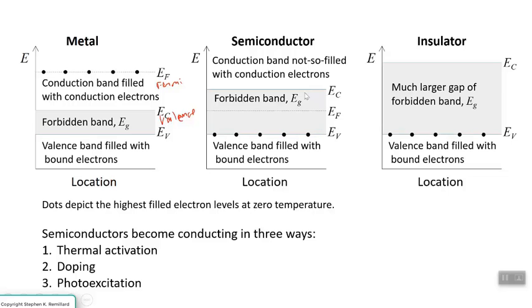which is what we practically do with semiconductors, where we put states in the gap and then have a very small ionization energy to get electrons in the conduction band. And then there's photoionization, where you send a photon along and it hits a valence electron, and it gets knocked into the conduction band. That's the principle of operation of a photodiode or other photoconductive materials.